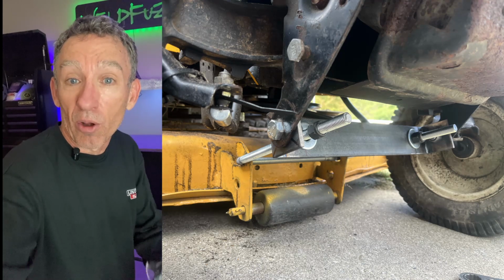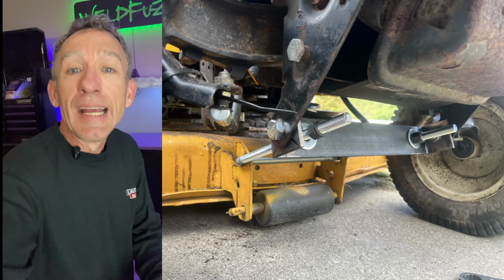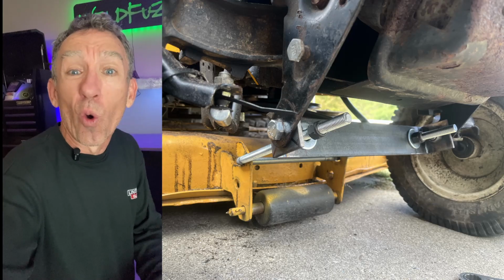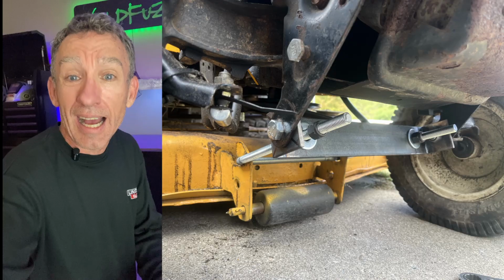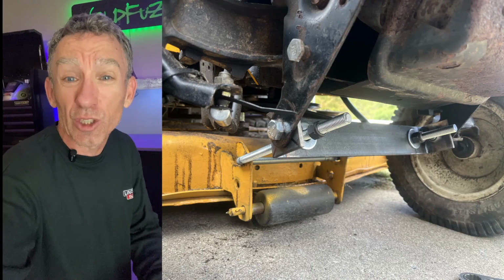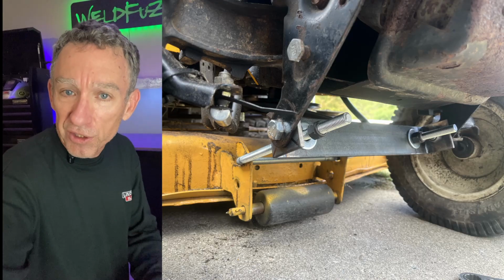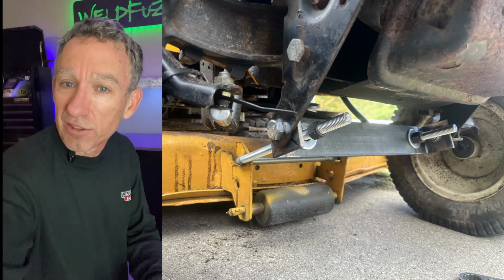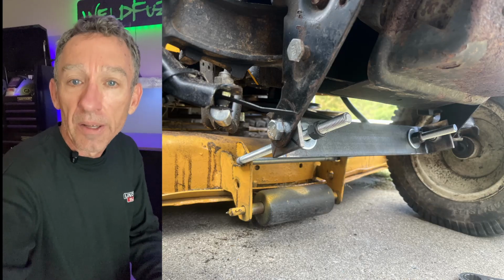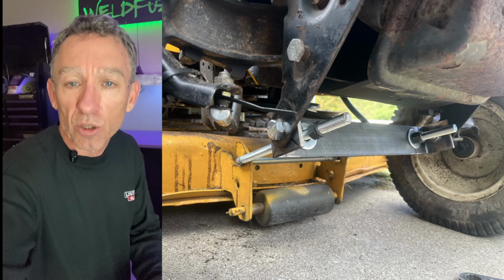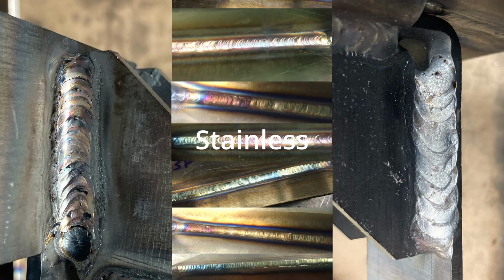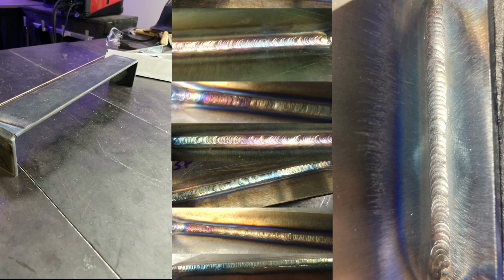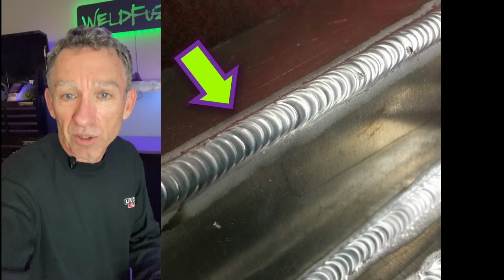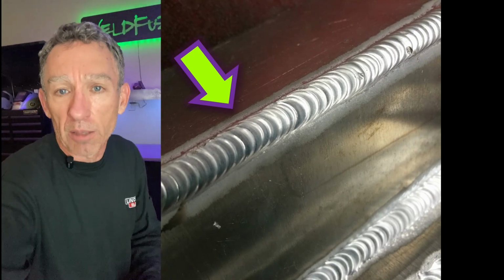We got this thing going back on the lawnmower. Remember, when you're welding carbon steel, clean it, clean it, clean it, because it's going to be oily, it's going to be greasy, it's going to hold on to oxides that make welding a whole lot more difficult, especially with TIG welding. When you jump over to stainless, stainless doesn't have that same issue, right? It's not absorbing those things into its oxide layer. No, the oxide layer is stainless. It's chromium oxide. So usually people go from welding stainless because it looks the best, and they start TIG welding mild steel, and they're like, wow, that looks like poop. And it kind of does, because mild steel is a lot dirtier than stainless steel. Switch over to aluminum, whole different animal, whole different ball game.